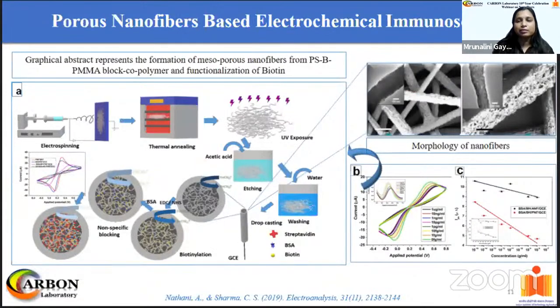Now the last one is porous nanofibers based electrochemical immunosensor. Here we first prepared nanofibers of polystyrene polymethyl methacrylate block copolymer. As described earlier, the PMMA phase was thermally annealed, then degraded by UV exposure and etched out in acetic acid to achieve mesoporous nanofibers of polystyrene. The porous nanofibers displayed the presence of higher surface concentration of carboxyl groups needed to bind with biotin.